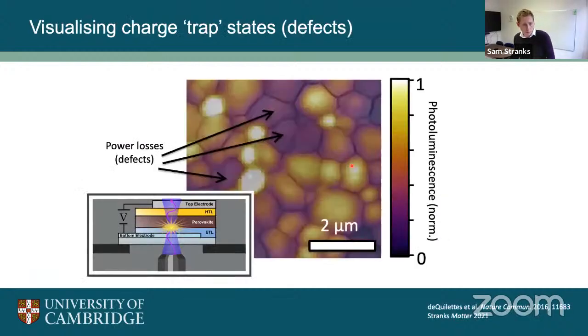Another thing we do is we zoom in on these materials. We use microscopes to look at the optical spectroscopy of these materials again. So this is a solar cell put under the microscope, and you can see a perovskite solar cell in particular, and you can see that these materials are actually made of grains. You see these grains making up sort of a mosaic pattern. That's what you see here. And the color on this map is actually the light coming out. So when we put light in, now we're looking at the light coming out.